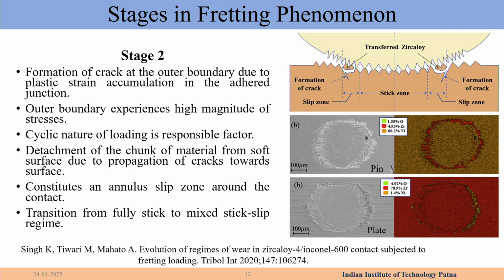So stage 2 is formation of cracks at the outer boundary due to plastic strain. So the outer boundary of the stick region, which is a circle, you can see this here at the center, this is sticking here, and these cracks start forming, and the cyclic nature of loading is a responsible factor. It is very easy to understand that the center part is sticking and you are moving it, at very small amplitude. So what will happen to the part outside that? It is going to detach from there. So you will start getting cracks. This is what we understood, and from the experimental we see this. And now over time, because of the cracks forming, this stick region actually starts becoming slip.